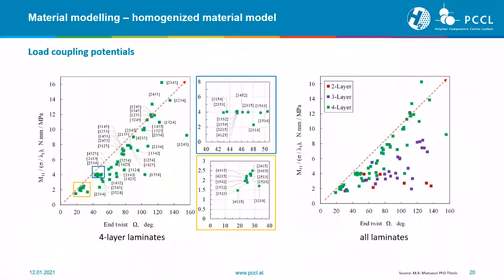Ending up with a lot of dots when we think of a moment as a function of the end twist, we see where we can achieve the highest load coupling potential based on the material model we developed, and also based on the theoretical observations we have made so far. Here, we are still on a theoretical way, and to bring this to reality, we also have to measure this end twist. We have to measure this moment, which we can receive with our different layers.